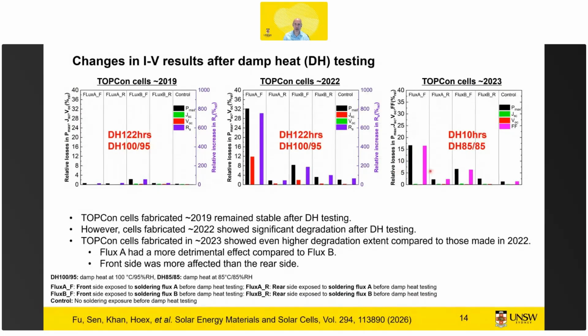bars look a little bit lower, but we had to reduce the testing time by a factor of 12, and we had to dial down the temperature by 15 degrees, which is a massive difference. So that's at least a factor of 4, roughly, in terms of degradation rate that we had to tune it down. So these cells were significantly more sensitive. And this is consistent, as mentioned, with other testing that we've seen as well.